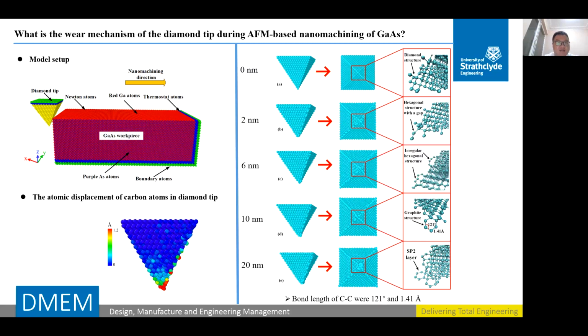Finally, at a cutting distance of 20 nanometer, the presence of a clear sp2 graphite layer structure was observed. This phenomenon suggests the apex of the diamond tip transformed from the initial sp3 diamond lattice structure to an sp2 graphite lattice structure. From this, I can infer that graphitization governs the wear mechanism of the diamond tip during AFM-based nanomachining of gallium arsenide.